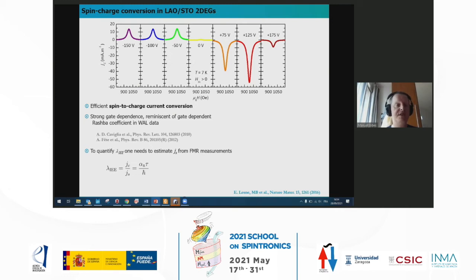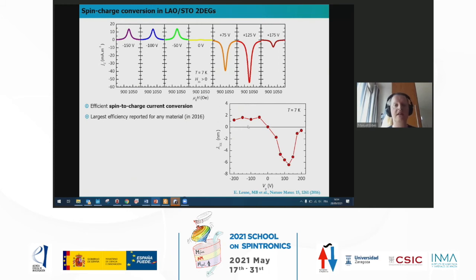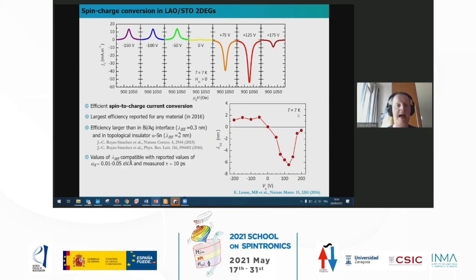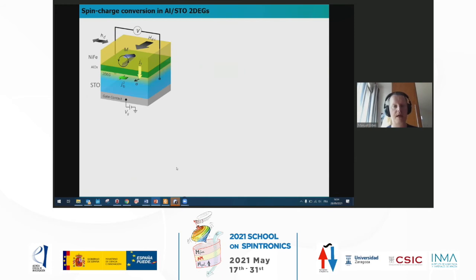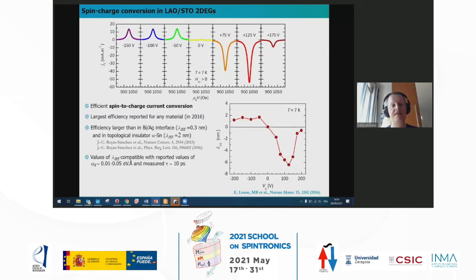So we can quantify the efficiency to see how good we are compared to other systems. So we need to quantify the spin current that we inject. We know how much charge current we produce, and we extract lambda values on the order of a few nanometers, which is larger than other materials, even topological insulators, although I must say that this was at low temperature. And in fact, the values that we get are quite compatible with what you would calculate from the Rashba coefficient, a few tens of meV angstrom, and tau on the order of 1 to 10 picosecond. So here you see that the effect is large, despite the relatively low amplitude of the Rashba coupling, because we have a 2DEG and we have a much longer scattering time than in metals. Okay.